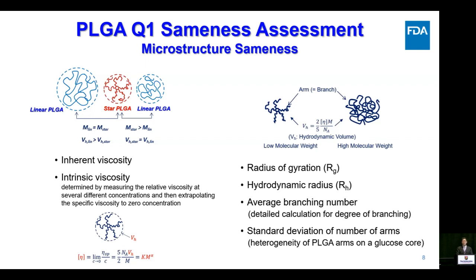And so we need some more information, also from lots of ideas in Dr. Park's talk. The first is the hydrodynamic radius calculated from the hydrodynamic volume, and also the radius of gyration. What the radius of gyration is, previously Dr. Kinam said, is the root mean square distance from the center of mass. And so if it has more polymer chains dense close to the core, the radius of gyration is smaller and smaller. And also there is another need for more information on how many arms are attached to the core and what their standard deviations are.